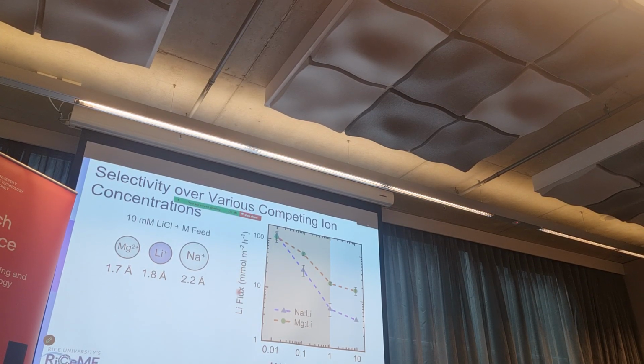We measured the lithium flux versus the molar ratio of the competing ion, M, versus lithium. The triangles represent sodium and lithium, showing the ratio of sodium to lithium in a mixture, and the green circles represent magnesium and lithium. A ratio of 1 means equal molar amounts of sodium and lithium. Here we have very little competing ion, sodium or magnesium, and much more lithium. As you increase the concentration of the competing ion, the flux decreases.